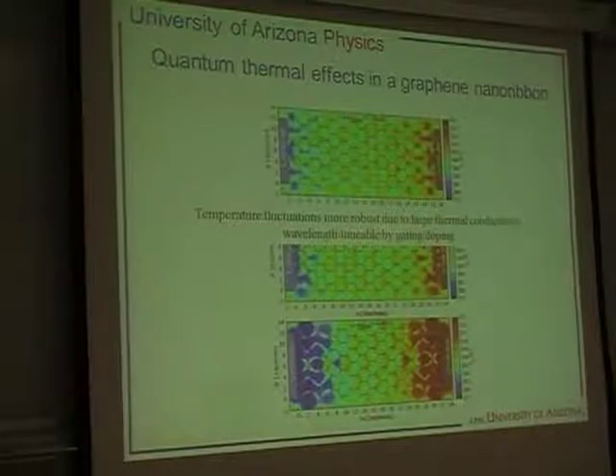So this is something which I'll explain in a moment, but I'd also like to point out, in addition to the fact that the wavelength of the thermal oscillations is variable or controllable by gating or doping, also, because the graphene is a very good thermal conductor, the coupling between the sample and the probe is going to be larger than it is in those other systems that I showed, so that's also favorable. So how can we understand this tunable wavelength?